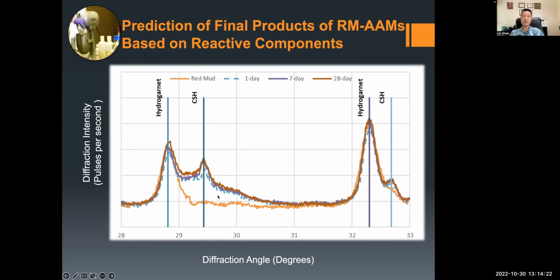And its crystalline phase is hydrogarnet. So hydrogarnet is not reactive. However, it is very strong, so it can serve as a filler and provide enough strength for concrete. Actually, the concrete can easily achieve strength of more than 100 megapascal.